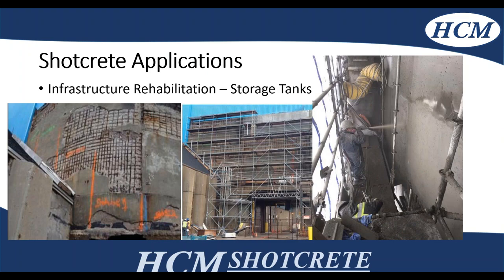This is an example of a storage tank we did at Compass Minerals down in Goderich. There's around 20,000 square feet of rehabilitation that occurred, and it was key to the client that we not disrupt any mine production. This work also occurred in the winter, so there were minimal shutdowns — the pour area had to be heated and hoarded. It was a dry mix process with fibers in it to ensure bond and shrinkage were kept under control.